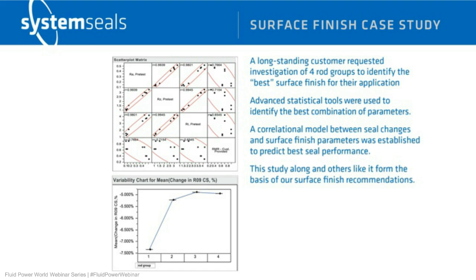In this particular set of experiments, we see that group 1 was the worst performer. Groups 2 and 3 were increases in performance, and group 4 perhaps dropped off a bit, or within the measures of statistical error could be equal to the parameters that we investigated in group 3. And so it's research like this and optimization experiments like this that allow us to take our surface finish recommendations from basic standard recommendations and actually choose ones that optimize a parameter, perhaps minimizing wear or maximizing seal life.